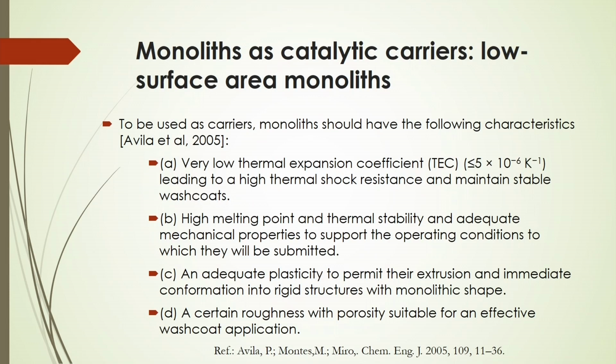Very low thermal expansion coefficient should be there, less than or equal to 5 times 10 to the power minus 6 per Kelvin, which may lead to higher thermal shock resistance and maintains the stable wash coat.